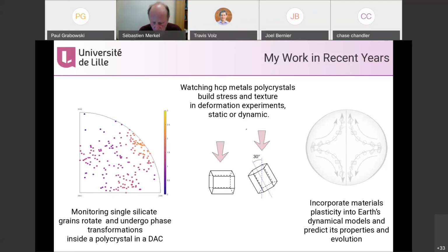There are projects here in Lille. Actually, there's a big group who do plasticity computations. They try to go up the scales from dislocations, to dislocation dynamics, to crystal, to polycrystal, to get to mechanical properties. But in my activity, I haven't done that. We go down with a geodynamical model, which is purely fluid dynamics. We get flow lines, and then we incorporate those flow lines into polycrystal plasticity to get the microstructures.